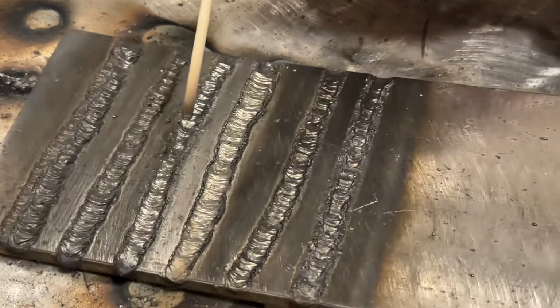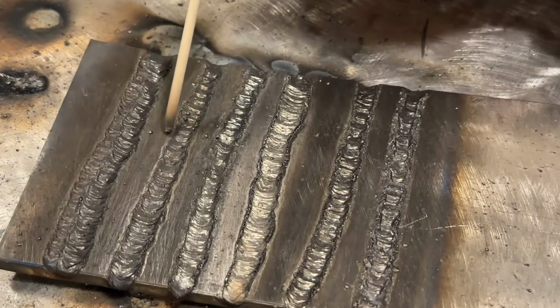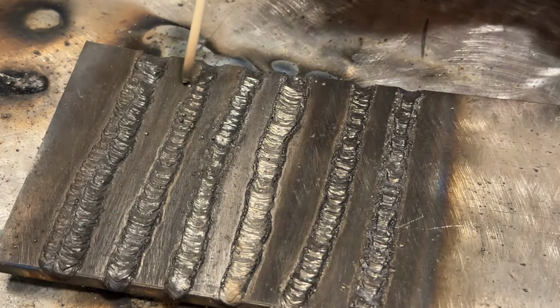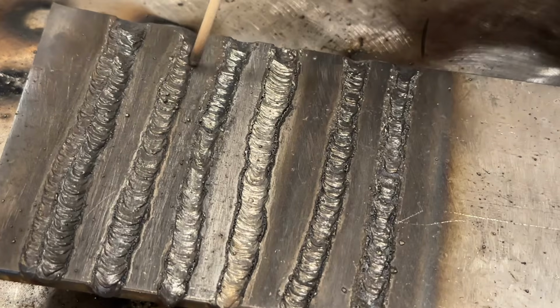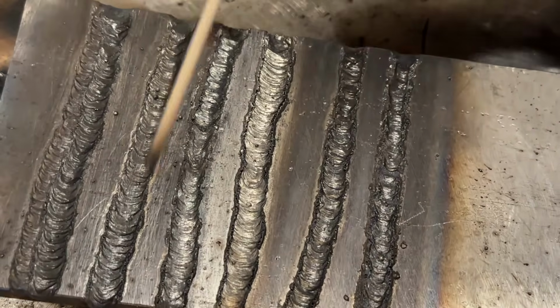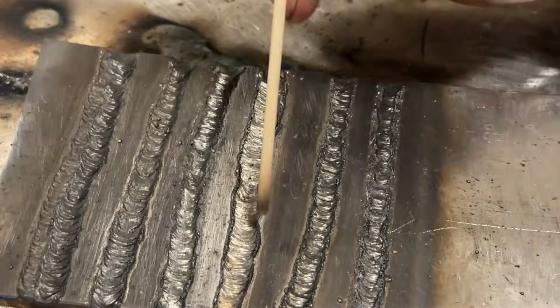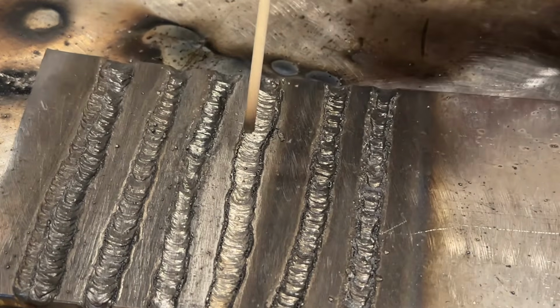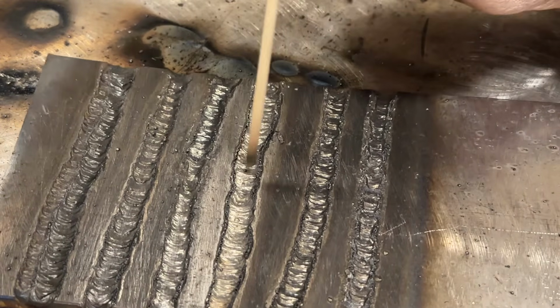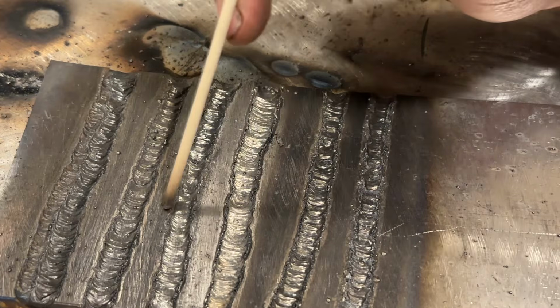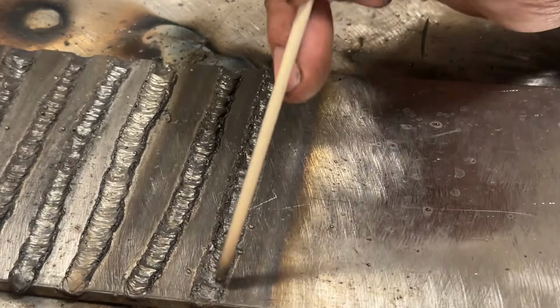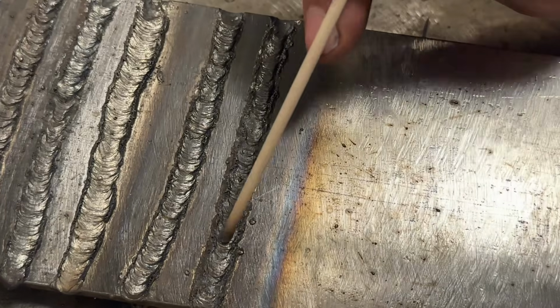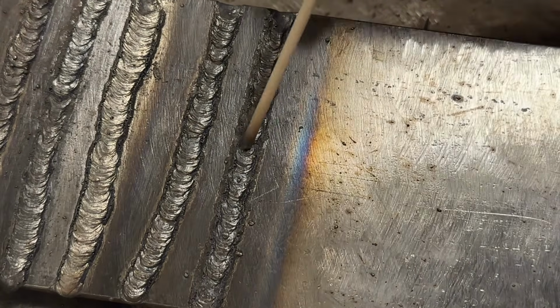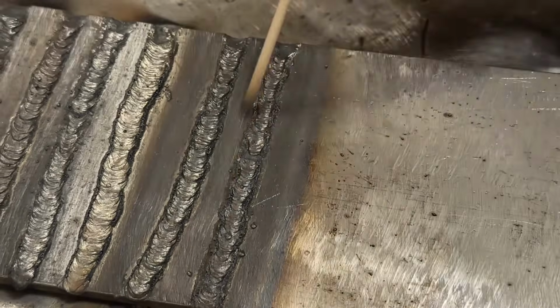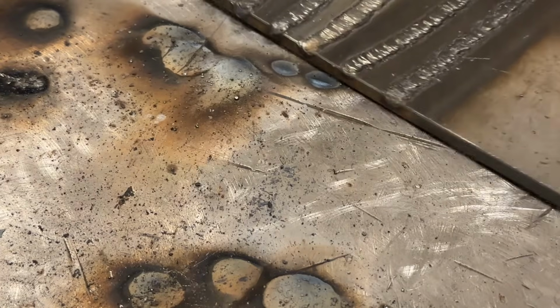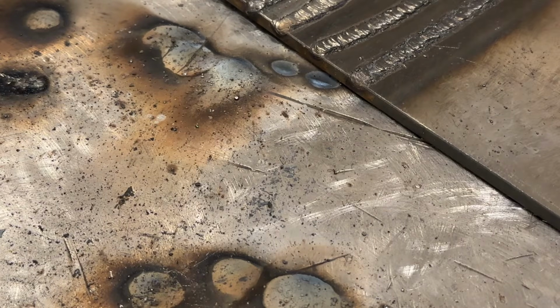And you can see the difference. You look at this, there's a little bit of spatter around here. I picked up a little bit too much speed here by the look of it, but there's a little bit of spatter here. And even this, where I was feeding too much rod in, but I had a tight arc, and I was going slow, not a whole lot of spatter. And then you come here, and this is really the only weld you see spatter in the weld. Now let me clean this a little bit better, and let's do a final look on that.